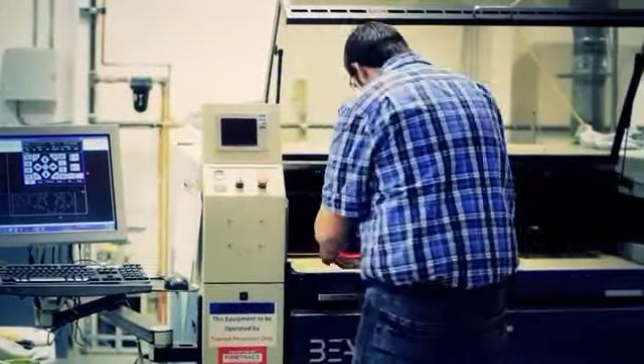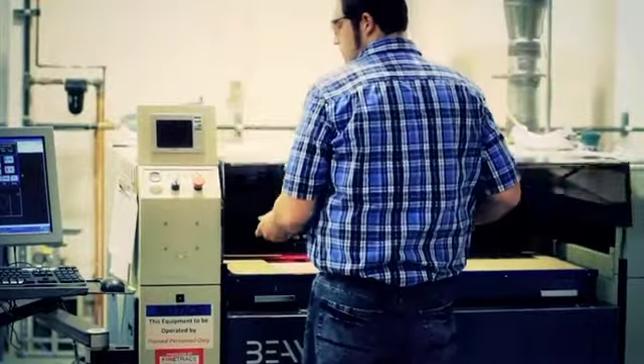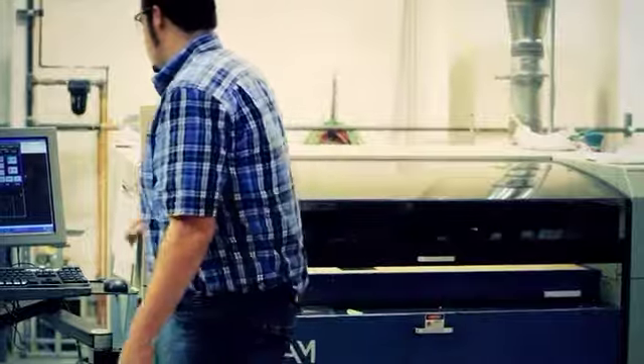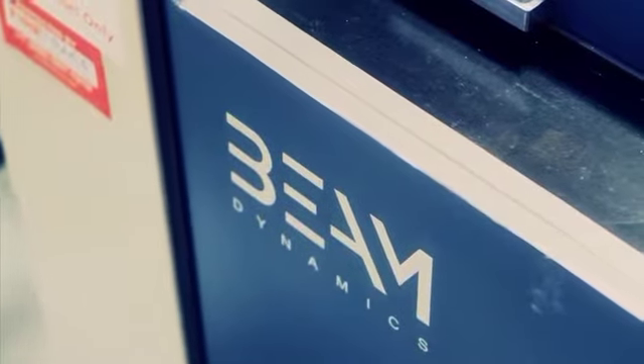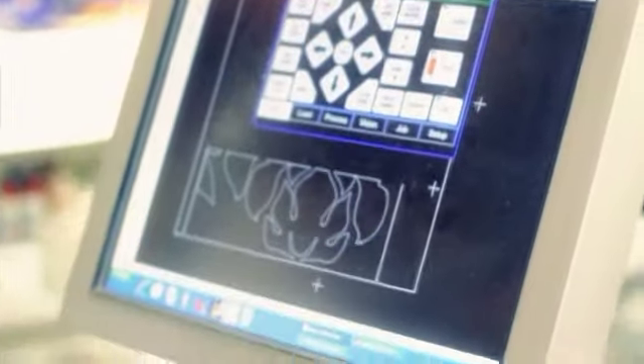Materials such as acrylics, on the other hand, laser cut very easily and smoothly, and they can be processed at thicknesses upwards of 1/2 of an inch. Above thicknesses of 1/2 of an inch, special considerations often need to be made for laser type, laser power, and feed rates of the material that sometimes has to be manipulated through some experimentation.